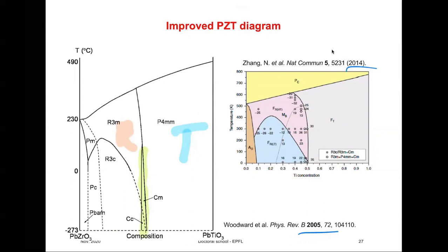And then there are other researchers. This one is by Glazer, a relatively recent result in which he showed that this whole field here of rhombohedral material can actually be considered to be monoclinic, which changes as we keep adding titanium. It actually changes the monoclinicity, however you define it. And so that large range here toward the morphotropic phase boundary is actually a monoclinic phase.